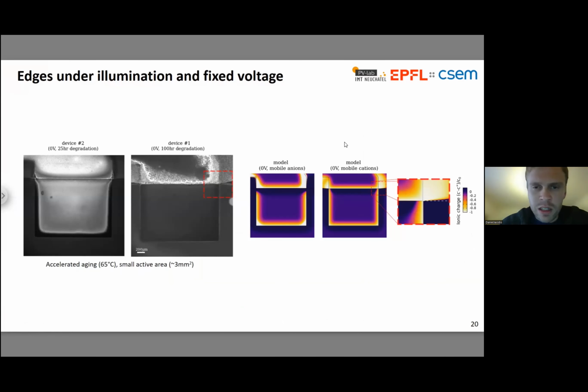So again, I can apply my models to see whether the patterns of degradation here match with what we expect based on lateral ion migration, and the models do quite well. Here I'm showing two different devices on the left-hand side, again, photoluminescence images. They've undergone different periods of degradation, both at short circuit. And you can see the patterns on the right-hand side predicted by the models.